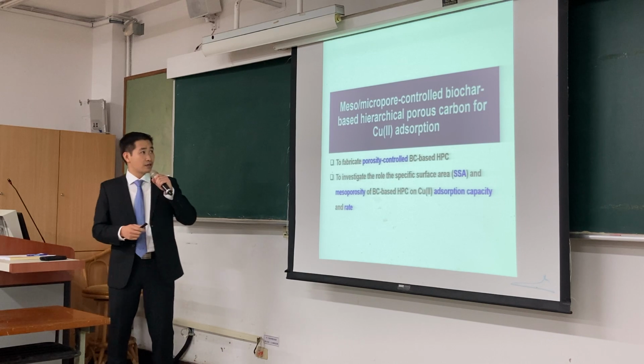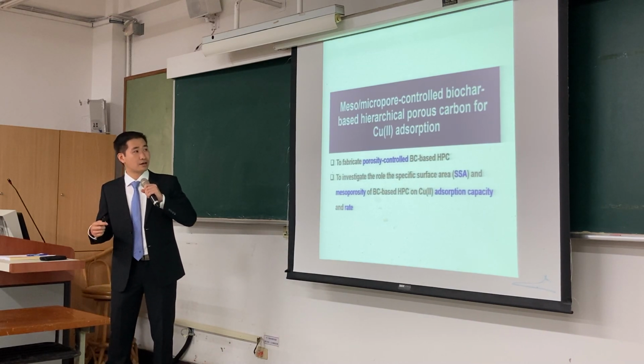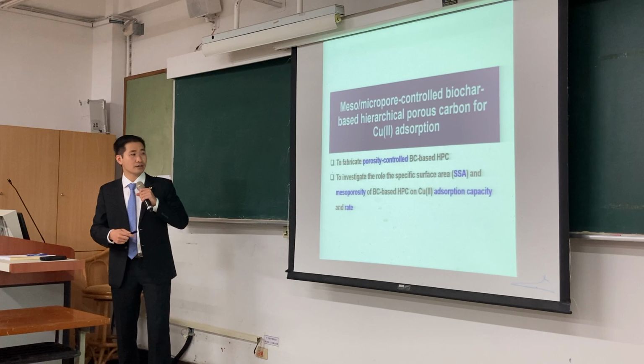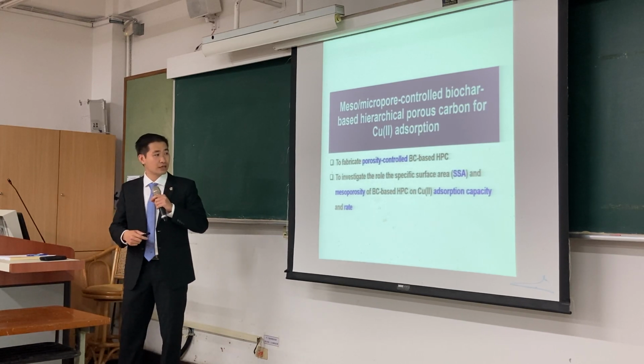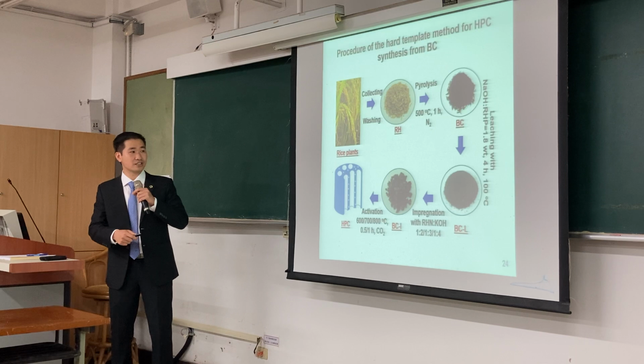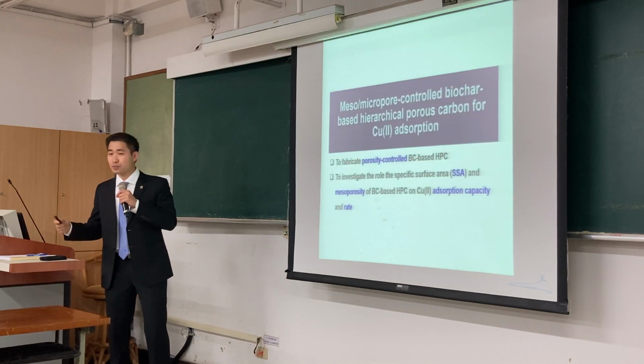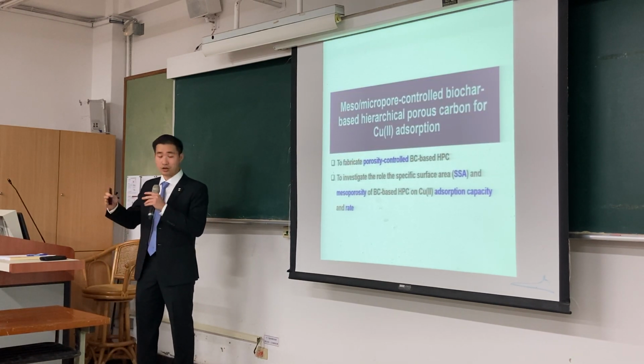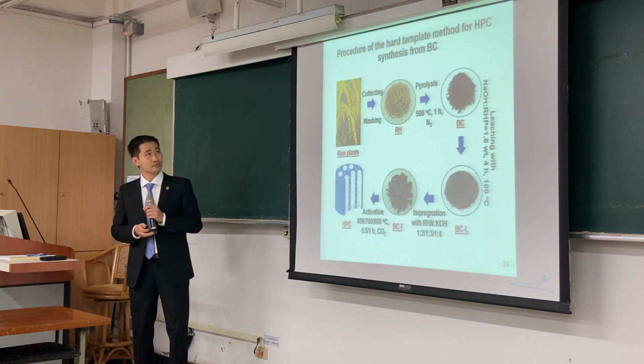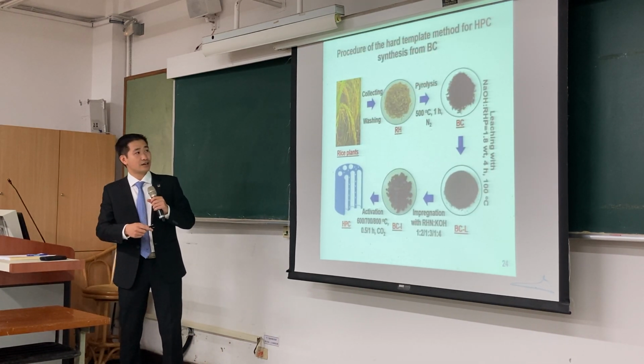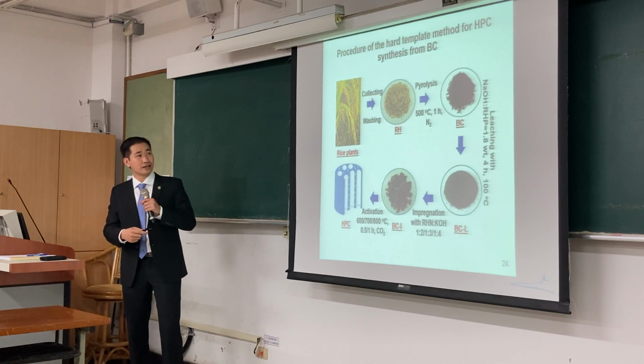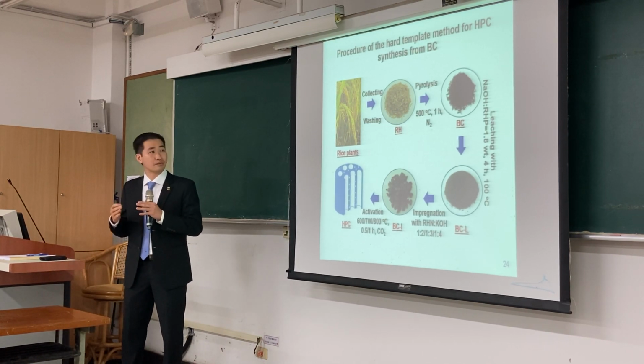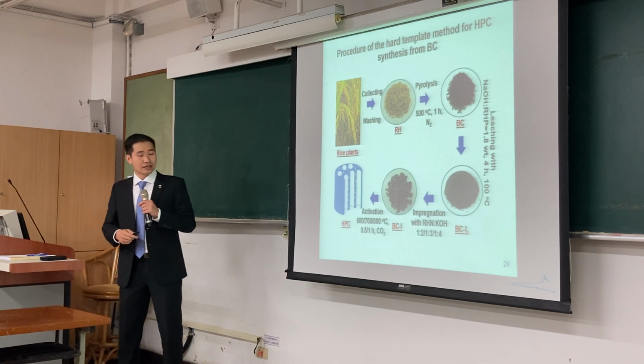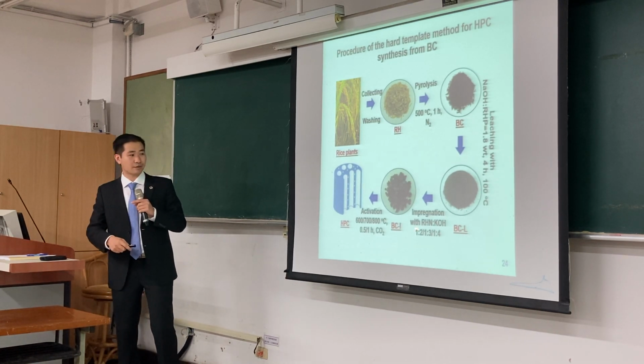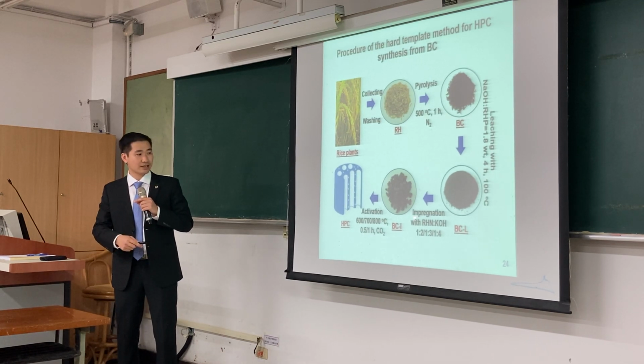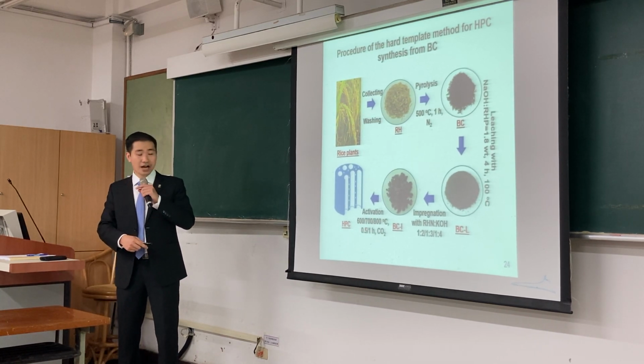In my first scope, the HPC was fabricated with porosity control to investigate the role of specific surface area and mesoporosity for copper adsorption capacity and rate. As we can see, the HPC was prepared from rice biochar by the template method. The porosity was controlled by changing the activation agent mass, activation temperature, and activation time.